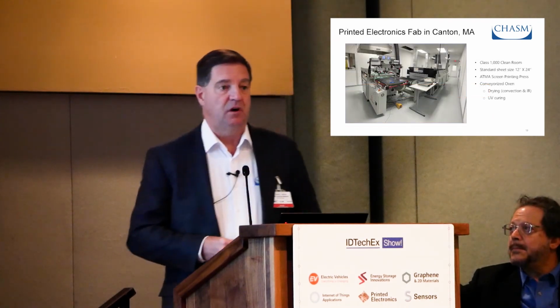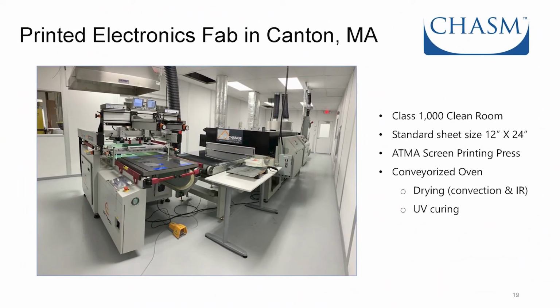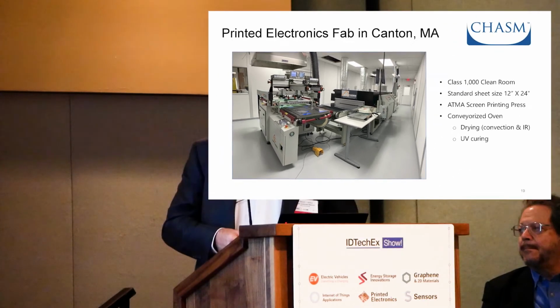This is a picture of the printing press line that we have in our facility in the Boston area. It's in a Class 1000 clean room. We've standardized on 12-inch by 24-inch sheet size. It's a state-of-the-art Atma screen printing press with dual cameras that allow for excellent layer-to-layer alignment. It's fully automated so we can capture all the printing process recipes. We have a conveyorized oven that can do convection drying, infrared drying, and also UV curing.